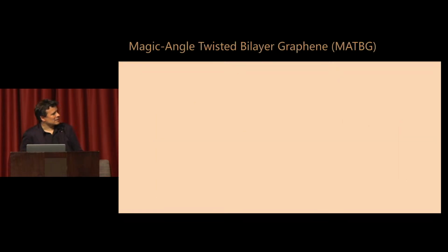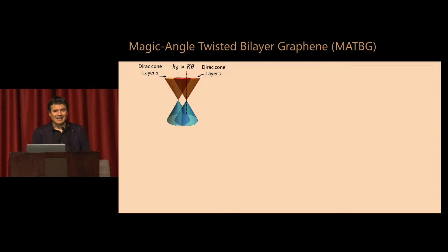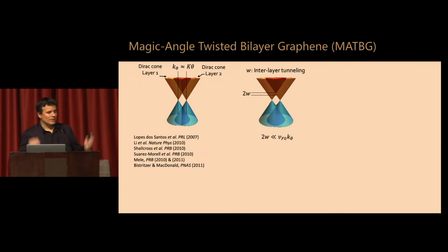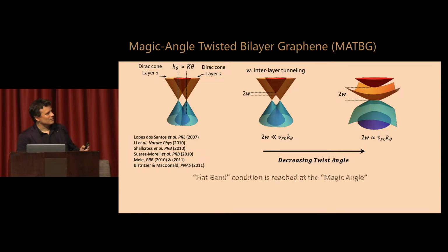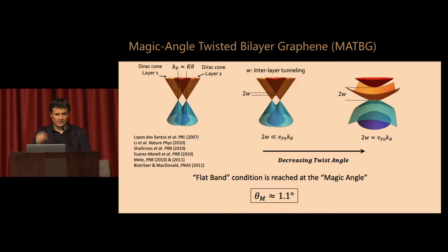For the experts, just one slide intermezzo: the Dirac cones of graphene, from the electrons in layer graphene 1 and layer graphene 2, when they get close together, lead to a band repulsion, which pushes one band to 0 energy, and you reach a flat band condition. That flat band condition is at the magic angle, and it's 1.1 degrees for graphene on top of graphene, due to the tunneling of the electrons between the layers, okay? This was theoretically predicted, that the electrons would go very slow, but that was a single particle physics prediction. Nobody knew what would happen when you put many of those slow electrons in graphene.